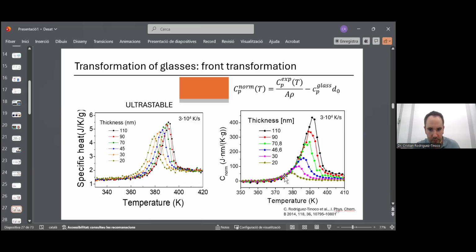Of course, for the 20 nanometer thickness film, this front will travel until it consumes the whole glass, and when it consumes the whole glass, the heat capacity goes to 0 because there is nothing else to transform. If the sample is 110 nanometers, the front can travel a longer distance until the whole glass has been consumed. And then again back to not 0 but a low value. So this is the front propagating into the bulk.